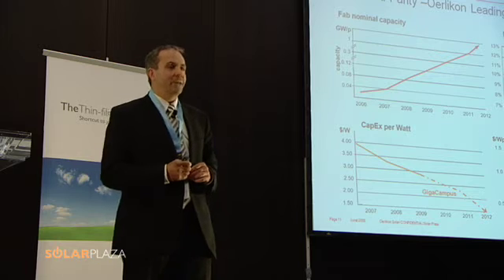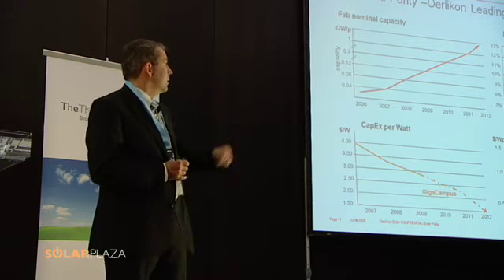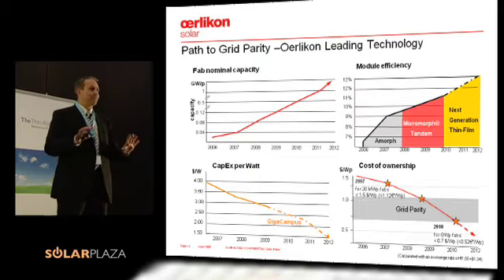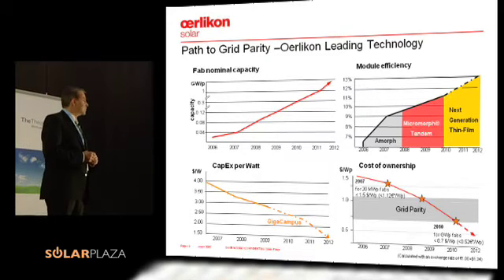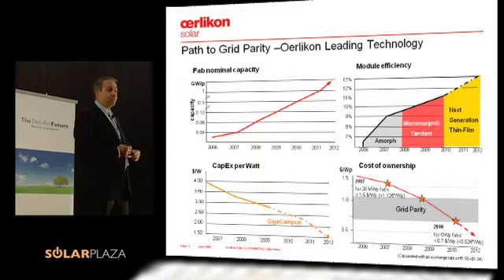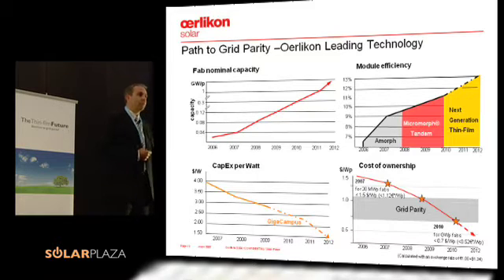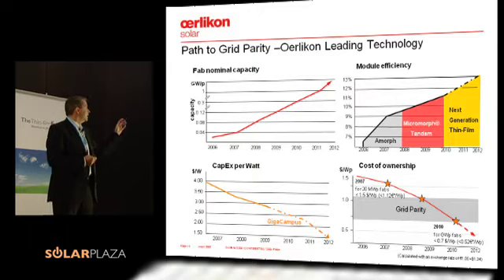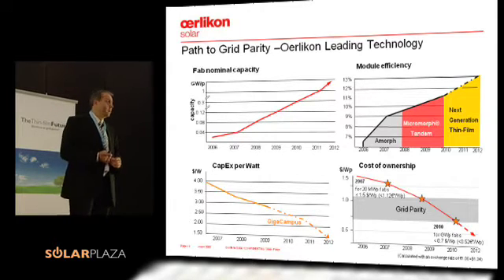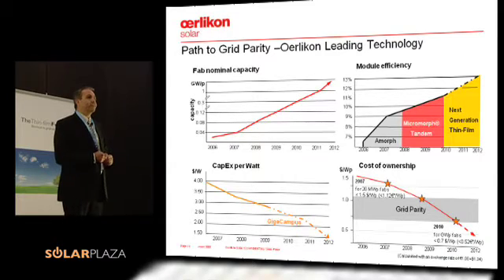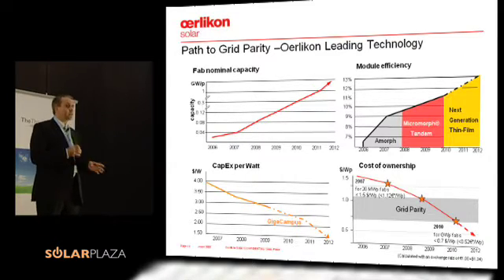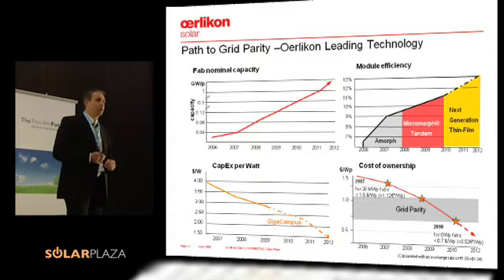The key part will be executing fast and having the right technology. On the top right side I see the module efficiency. We started with amorphous technology — even though five or six years ago everybody said amorphous silicon is not really a product for this market, it became one. But clearly for us the main focus is micromorph. End of 2007 we introduced micromorph, which allows us to go above 9% efficiency, and it should lead well above 10%. After that there will be next-generation thin-film applications, still silicon-based but with combinations or additional developments.